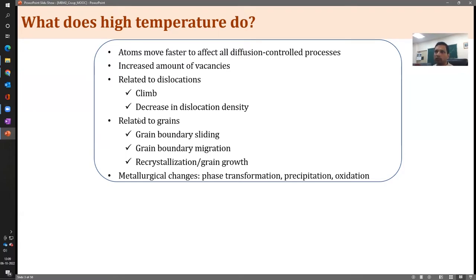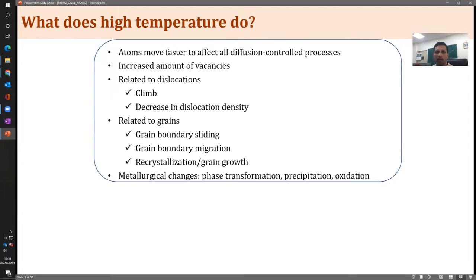At the grain level, several phenomena can be affected by elevated temperature. One very important phenomenon is grain boundary sliding, which aids the creep mechanism. There is also grain boundary migration, meaning grain growth can take place, which in some cases may also mean degradation of the material. At higher temperature, recrystallization also takes place, and if it is a work-hardened material the strength goes down.